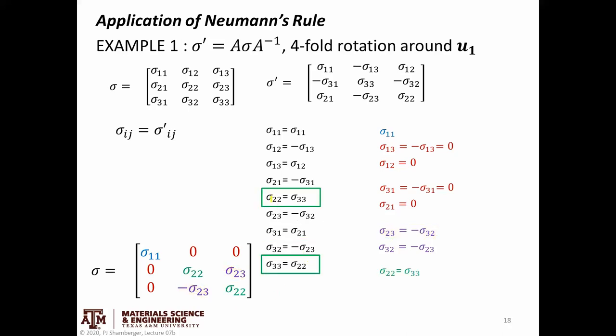Finally, σ₂₂ equals σ₃₃, and σ₃₃ equals σ₂₂ — that just means the middle element and the bottom-right element have to be the same value. I'll call them both σ₂₂. So we've gone from nine independent elements originally to just three independent elements: σ₁₁, σ₂₂ (which also appears in the bottom-right), and σ₂₃ (with negative σ₂₃ in the other off-diagonal position). This has drastically reduced the scope.